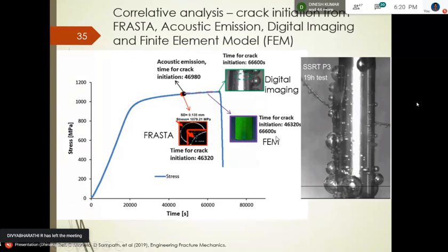Yes. And then we have this finite element simulation as well, but it is also off by some factor. But I think the most important one, the experimental validation, is from acoustic emission, which validates the findings of FRASTA. So, what are the implications? Early crack initiation and subcritical cracking is observed in the slow strain rate test, which is not a better way of evaluating the susceptibility. So we need to go for a fracture mechanics based test.